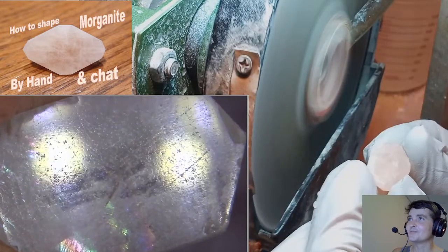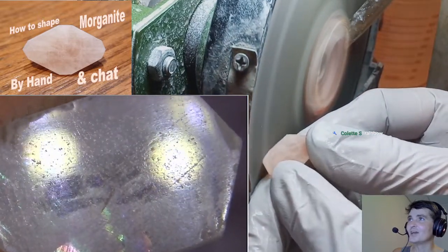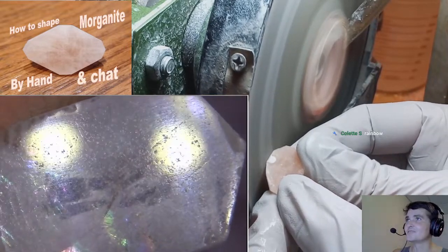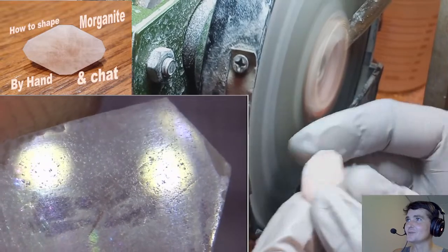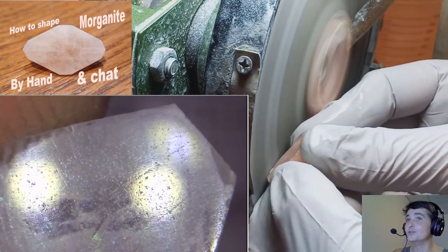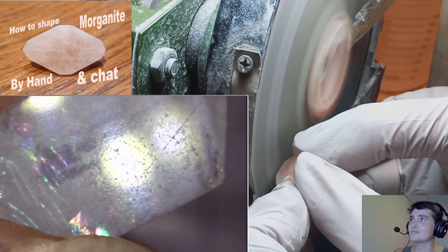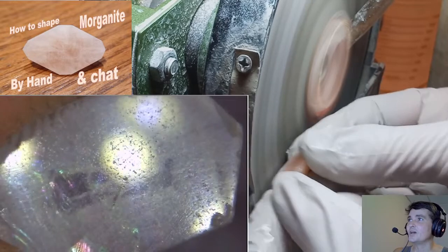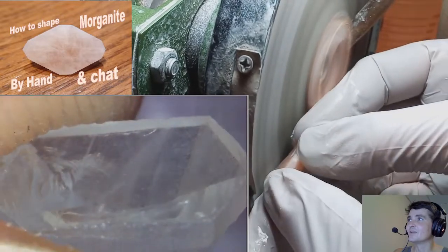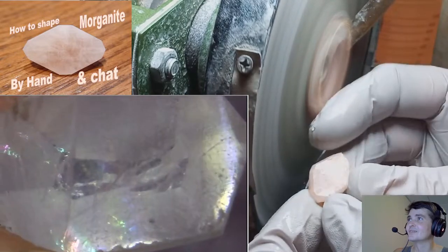You can see the difference between the pits from chip-out during the scratch and those big long swoopy pit lines — those are from the thousand grit. And if you look at the actual texture, the swoopy lines are going one way and the texture is going another way — that's from the 2000 grit polish. So that's what you'd have to sand out with your 8000 grit. But I still need to go deeper with the 2000 to get rid of the orange peel or pits. The depth of the pits is how deep I need to go. Maybe more like a 1000 cerium or a 4000 diamond would get rid of that. Beyond that one big crack in the middle, all the littler cracks are not really big concerns in terms of the gem falling apart.